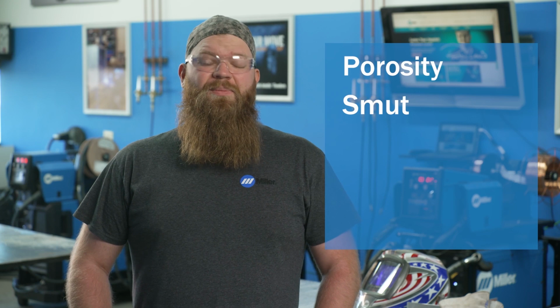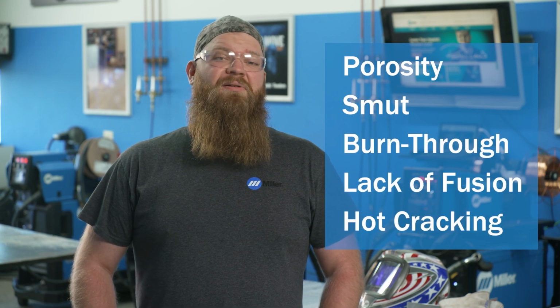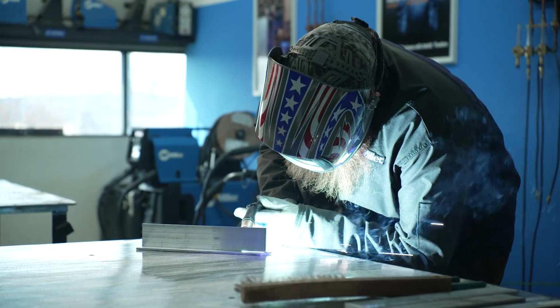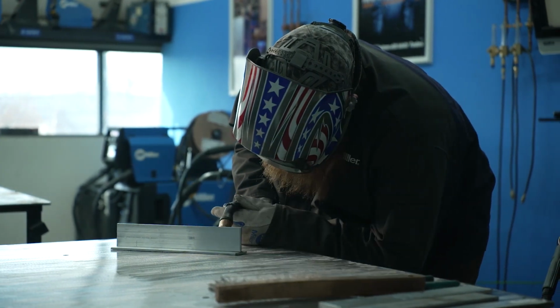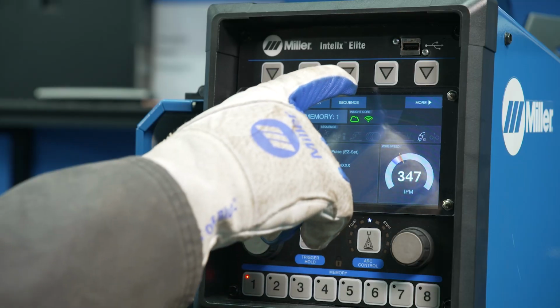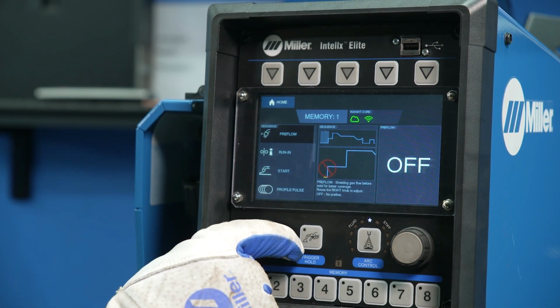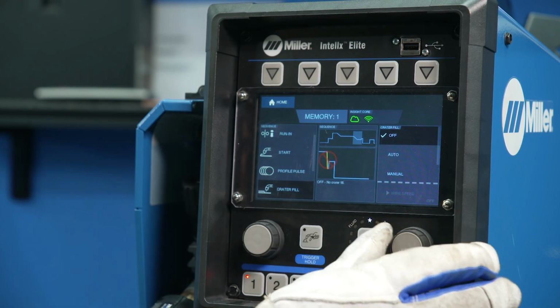Porosity, smut, burn-through, lack of fusion, and hot cracking are some of these common issues. Hot cracking is caused by crack-sensitive bead profiles, using the wrong filler metal, or crack-sensitive chemistries in the molten weld pool. A common location for hot cracks to occur is in the crater of your weld. These are referred to as crater cracks. A common fix is to re-trigger and fill in the crater with a short weld. A more consistent and more efficient option is setting a crater parameter on your welder.